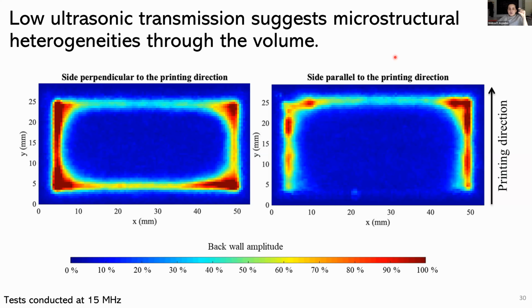Now, to begin with, these were fairly large samples, so they were an inch in height and width. So that didn't necessarily lend itself to very detailed analysis. So what we did is we went ahead and sectioned the samples and then rescanned them with our thickness independent method to get wave speed and attenuation on some of those thinner slices.